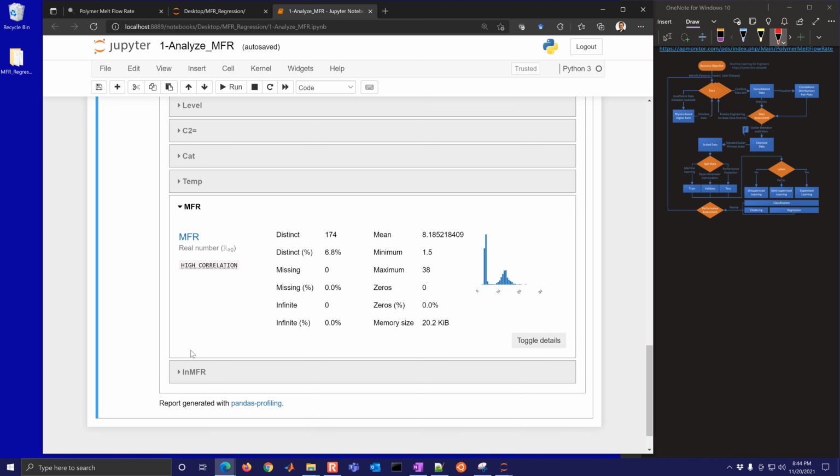All right, and then we have the MFR. And this one's kind of interesting because this one is a very high viscosity polymer right here, and this was a low viscosity. So what happens with this MFR is you heat this polymer sample and put a plunger on top, and this is the number of grams per minute that come out of that die.